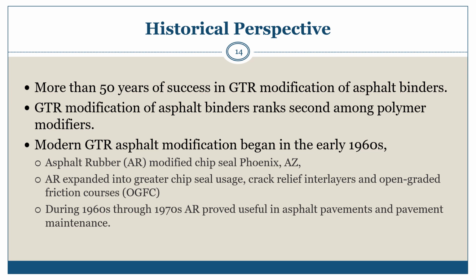Research on GTR modified asphalt binders over the last 50 years has shown favorable impacts of GTR modification. GTR ranks second among the most common asphalt polymer modifiers behind styrene butadiene styrene, SBS block copolymers. Modern GTR use in paving began in the early 1960s with a highly elastic asphalt rubber, or AR. The work expanded into larger chip seal projects along with other crack relief interlayers and open graded surface courses. During the 2 decades following, AR materials increased as they proved useful in various pavement maintenance functional applications, including asphalt pavement. But by far the greatest utilization during this time frame was maintenance applications.